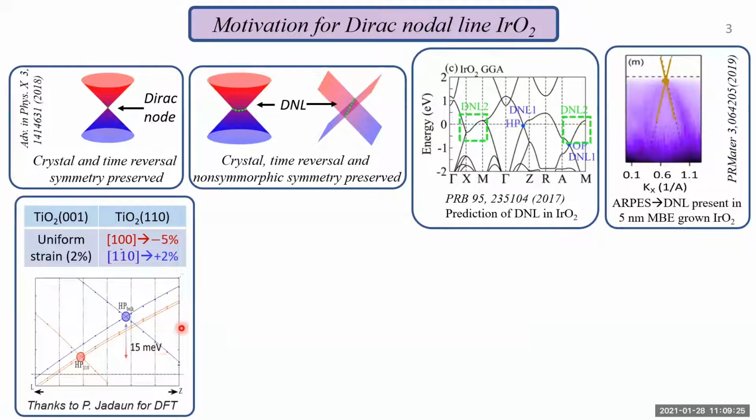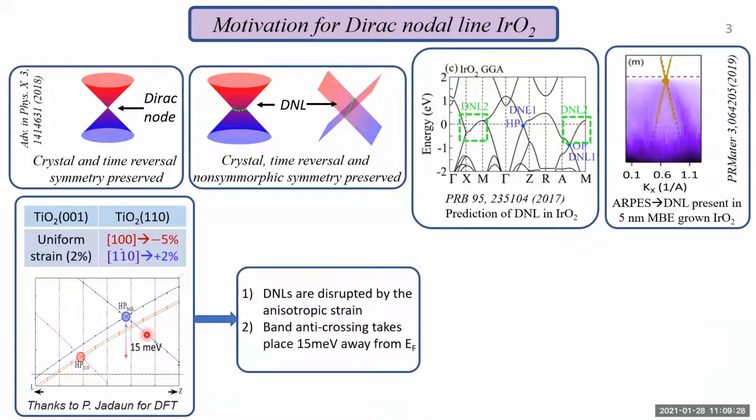Secondly, without the spin orbit interaction previously, it was 6-fold degenerate. But now, because of this anisotropic strain, this degeneracy is broken, and now it is fourfold degenerate. So we have band gap opening due to strain, but not due to spin orbit interaction. Together, this should actually decrease the spin Hall conductivity for 101 oriented films. Okay, so this is the argument, but we need to see experimentally what happens.